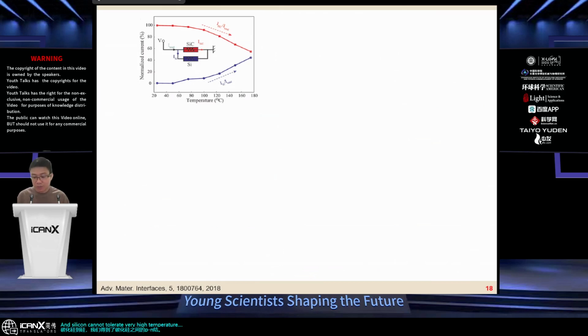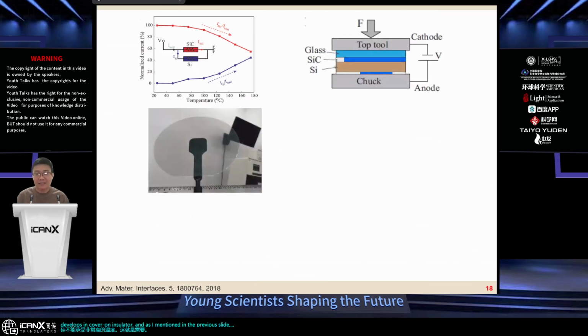So that's the need to develop silicon carbide on insulator. And as I mentioned in the previous slide, we can locally oxidize the silicon substrate to form silicon carbide on insulator, but it requires focused ion beam or e-beam lithography, and the yield is not very high. We want to have a more scalable process that can transfer the whole silicon carbide wafer from silicon onto insulator. One of those processes was to use anodic bonding to bond the silicon carbide on silicon wafer to a glass substrate. And then after you remove the silicon substrate, you will have silicon carbide completely on insulator like this, a transparent thick silicon carbide on glass wafer.